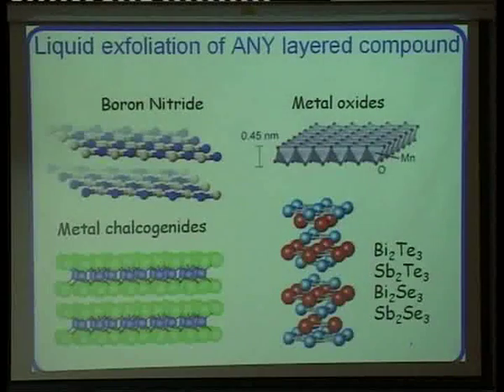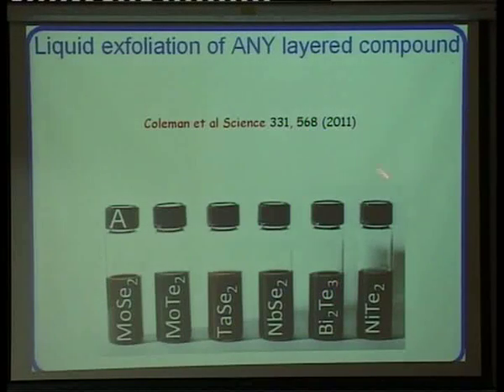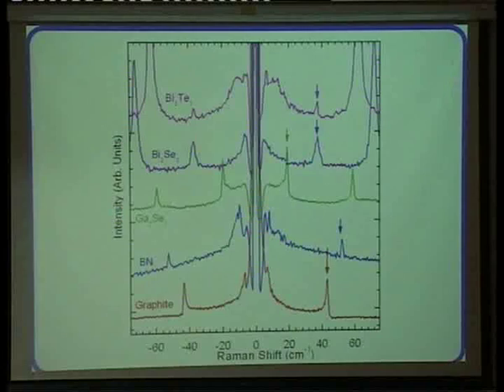But as I said before, we can already do, since 2011, the exfoliation in liquid and get all sorts of layered material liquid exfoliated. And of course, also in these materials, you have a shear mode that has mostly not been studied, and this is an example in the bulk of BN, graphite, bismuth selenide, bismuth telluride.